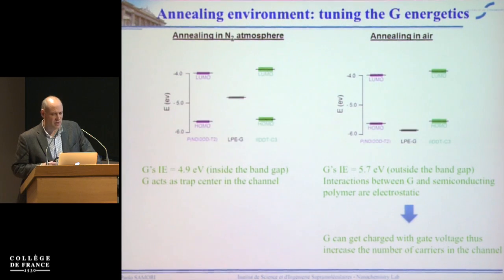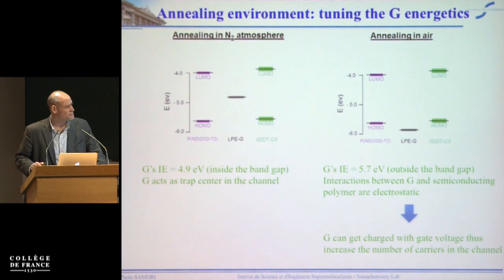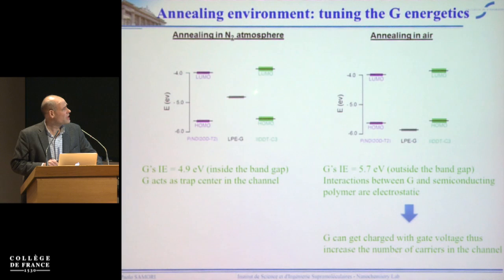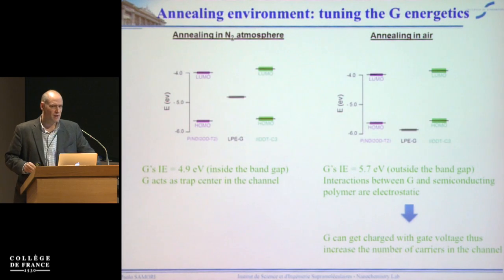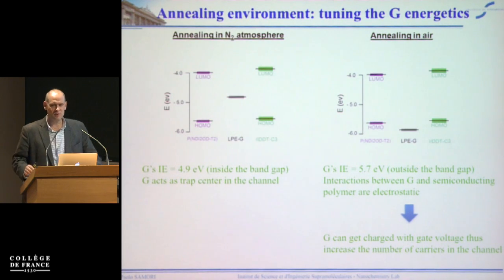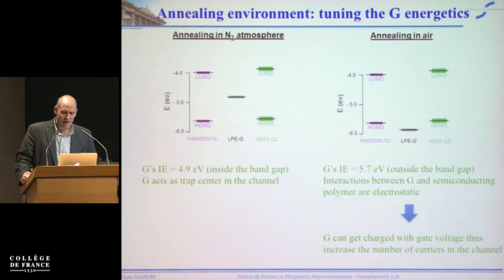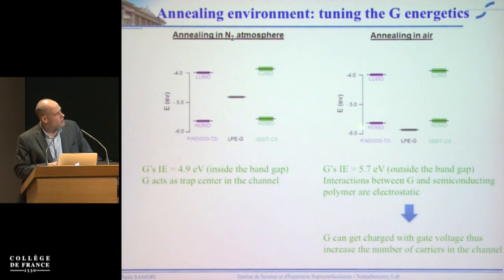Now, if you look at the energetics of your system, these are the HOMO and LUMO of the polymers. So this is the N-type, this is the P-type. They have very similar energetics. The ionization energy of the graphene annealed in nitrogen atmosphere lies at around 4.9. Surprisingly, when we do this kind of annealing at 400 degrees in air instead of in nitrogen atmosphere, the ionization energy goes up to 5.7. XPS did not show us any difference between these two different samples. So chemically, I'm not able to tell you what the difference is, but I can tell you that this is highly reproducible.